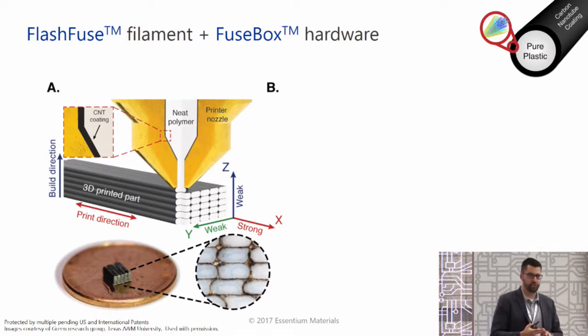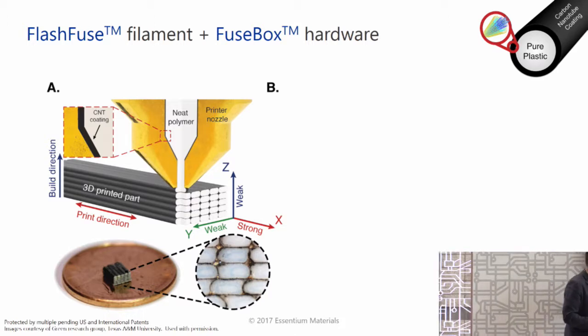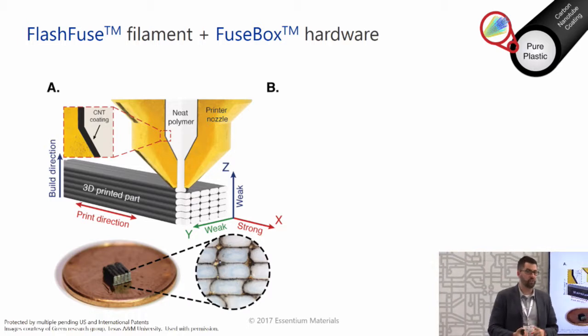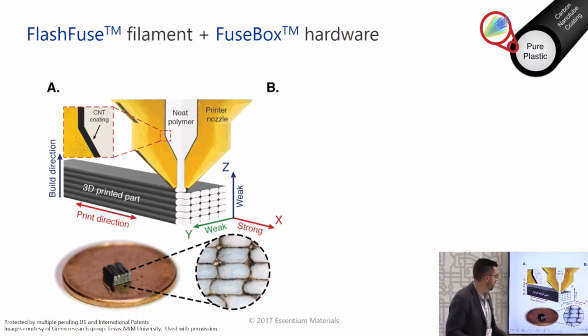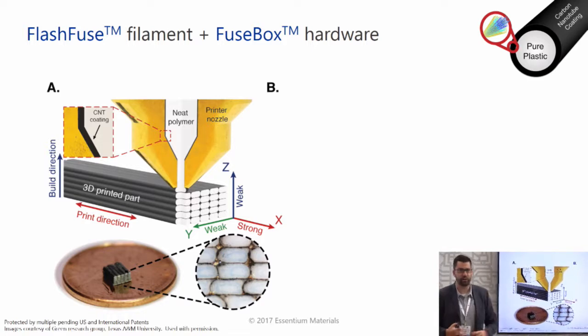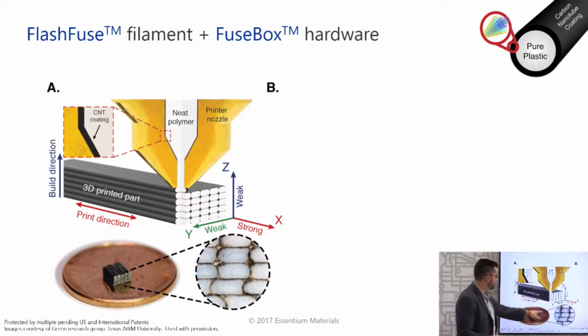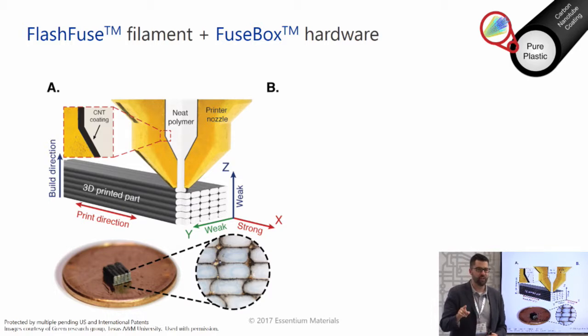So this is really important for two reasons. Number one, all the mechanical properties that you have in this core here, whether it's just neat, unfilled resin, or even carbon fiber or glass fiber filled polymers, all those mechanical properties are maintained. They're not interrupted by nanotubes. And the second thing that's really great is it keeps your costs down, because all the expensive materials, the carbon nanomaterials, are just used on the outside in a very thin film. So then you can see, even from very small parts, when you take a cross-sectional view, we do not get mixing. Our carbon nanotube composite stays highly segregated from the inner core of that plastic filament.